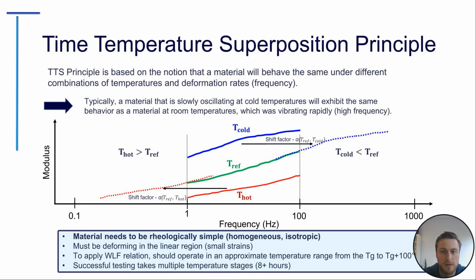For those unfamiliar with this principle, it's essentially based on the notion that a material will behave the same under different combinations of temperature and deformation rates—in terms of DMA, that's frequency. Typically, a material slowly oscillating at cold temperatures will exhibit the same behavior as a material at room temperature oscillating very fast with high frequency. So this allows you to run frequency sweeps at a set of temperature stages, and then shift your data to model the performance of the material at high and cold temperatures.